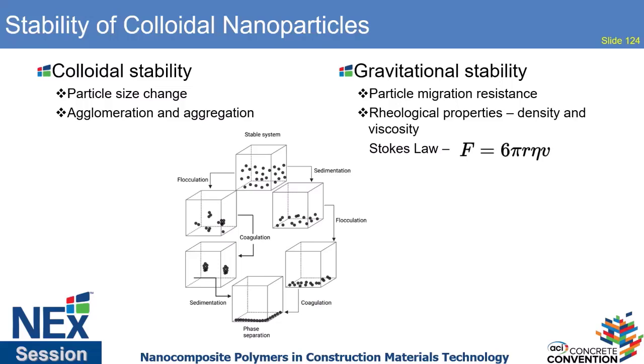So from Stokes' law, we can see that the force of the particle that needs to move through a viscous liquid is directly proportional to the velocity and the density of the particles. There is a schematic representation that's basically showing that if we don't have a stable system, aggregates or agglomerates and flocculates will form, and then they will eventually sediment. On the right side, it shows the degradation mechanism if we don't have the proper gravitational stability.